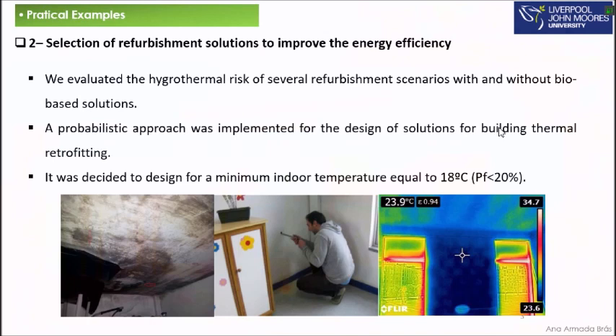We evaluated the hygrothermal risk of several refurbishment scenarios with and without bio-based solutions. Then we implemented a probabilistic approach, like a performance-based design again, for the design of solutions for building thermal retrofitting. It was decided to design for a minimum indoor temperature equal to 18 degrees, based on the hygrothermal monitoring and energy audit that we did during 2 years for these buildings. We realized that to ensure that relative humidity was always lower than 70%, so that there were no health problems for people, it corresponds to a probability of failure of 20%, which leads to an optimum minimum design temperature of 18 degrees. Because in the majority of these houses, the indoor temperature was around 14 degrees. So as you can see, it was very difficult to survive here during winter.